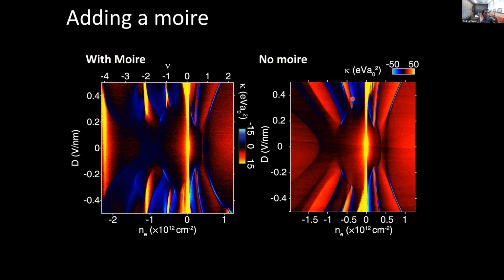I think the way to think about it is that the energy hierarchy here is that Coulomb repulsion is larger than the moire potential. So you already gap out all your other spin and valley flavors. You're left with one band, and then you have a weak moire potential, which will gap that out at the moire zone boundary. And then the same thing can happen for a half metal. And then there are interesting effects of Berry curvature and so on, but it's a very different type of flat band limit than in twisted bilayer graphene, for example.